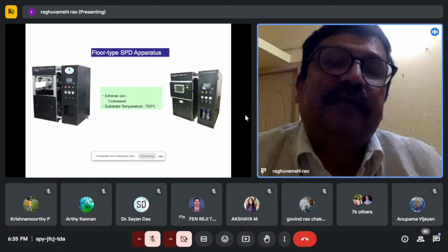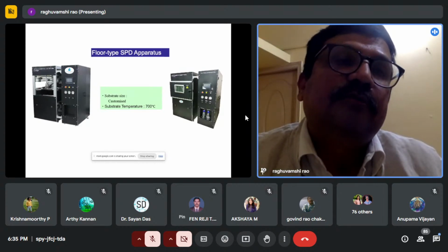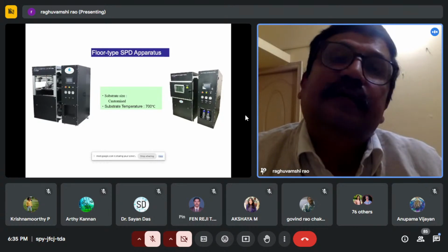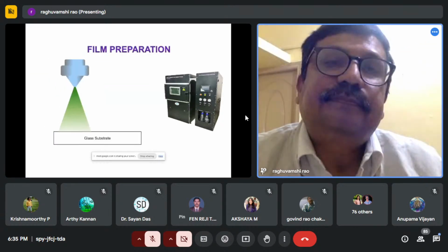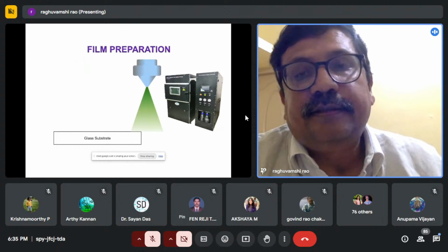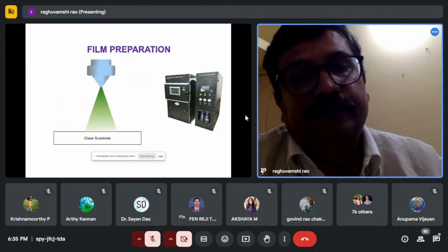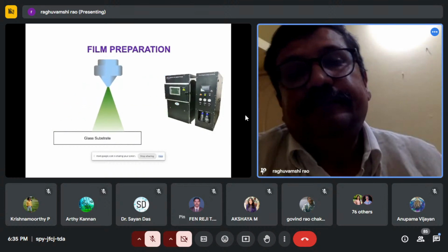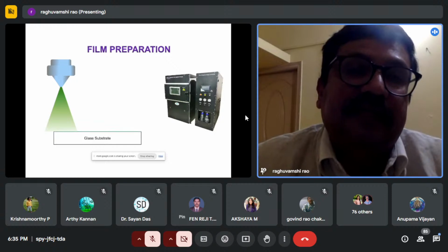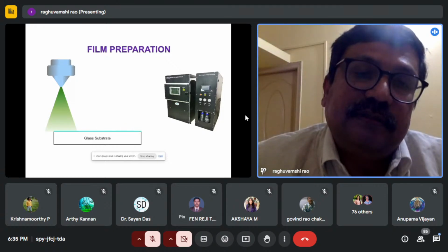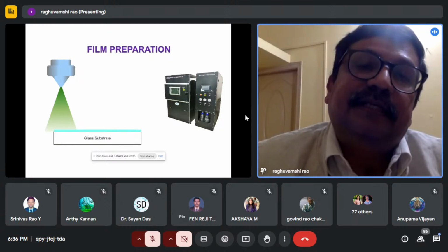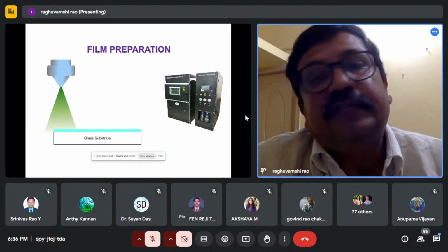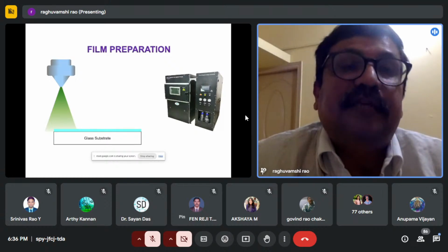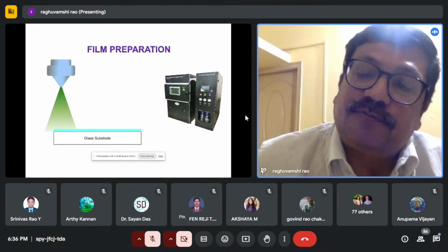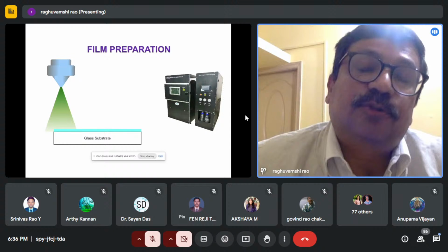Some of the devices that we manufactured and put to use, floor type of large area SPD apparatus systems. We also used a robotic device inside to move the spray nozzle across the glass substrate, and also for formation of the thin film over the glass substrate. And it can be tailored or monitored according to the thickness required, and the sprays and the cone size can be operated. We can use different types of nozzles here, air-based nozzles or ultrasonic nozzles.